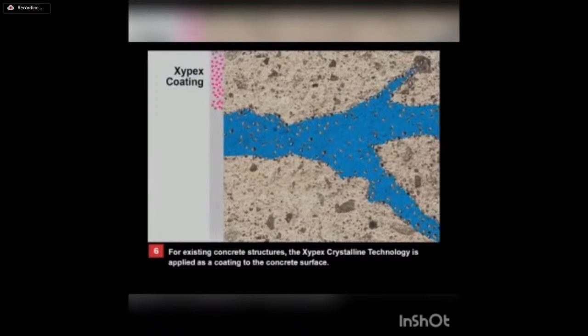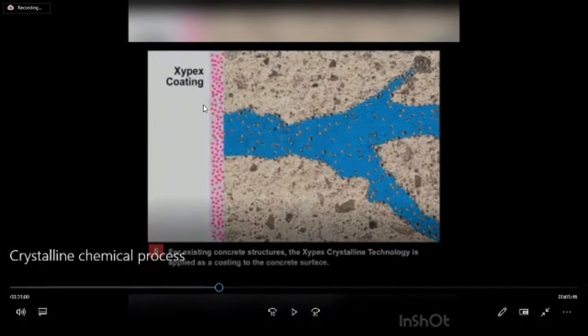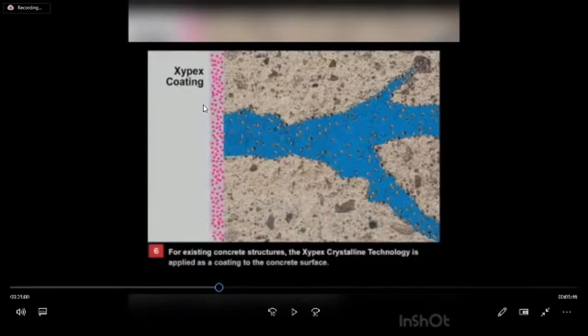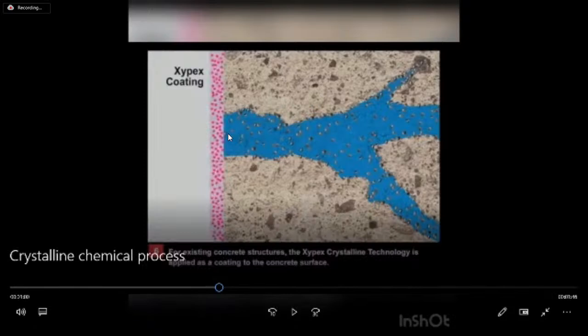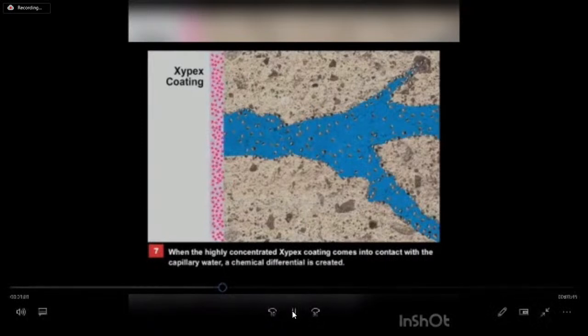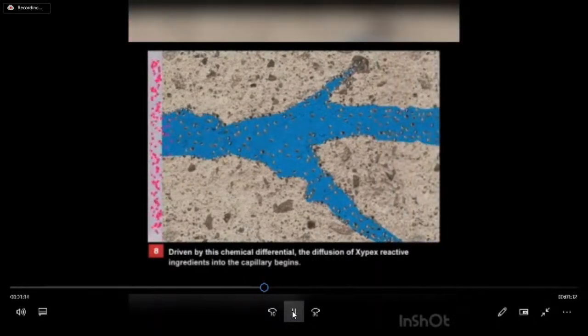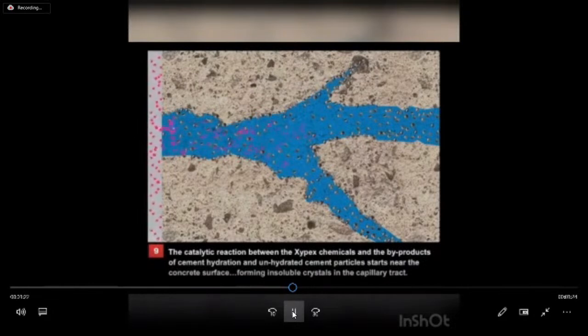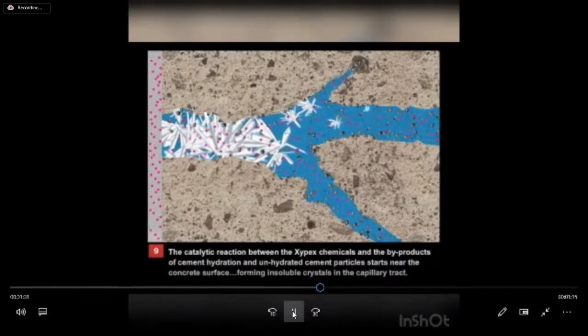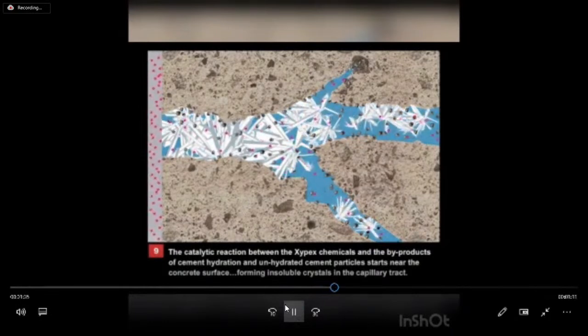For existing concrete structures, the Xypex crystalline technology is applied as a coating to the concrete surface. This red color is a chemical which we normally apply on a saturated surface. So the available water in the capillaries will form a reaction with the available free lime in the concrete, and this is the way they will form the crystals. When the highly concentrated Xypex coating comes into contact with the capillary water, a chemical differential is created. Driven by this chemical differential, the diffusion of Xypex reactive ingredients into the capillary begins. The catalytic reaction between the Xypex chemicals and the byproducts of cement hydration and unhydrated cement particles starts near the concrete surface, forming insoluble crystals in the capillary tract.